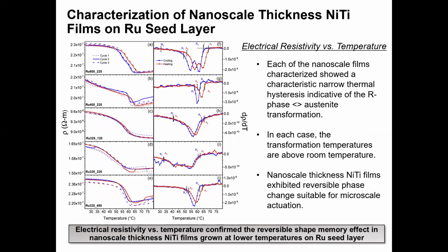This is looking at electrical resistivity measurements versus temperature. These measurements were made from room temperature up to 90 degrees. And the transformation temperatures were determined by looking at the derivative of resistivity with respect to temperature. In each of these films, the transformation was between austenite and R phase, and provided a third method of confirming that a nanoscale NiTi film deposited onto a ruthenium seed layer at temperatures as low as 325 degrees should be suitable for microactuation, and has promise to enable future integrations of these SMA films with CMOS and polymer materials.